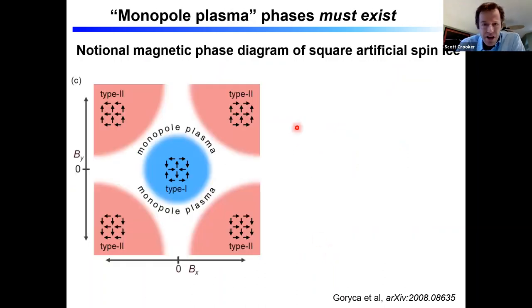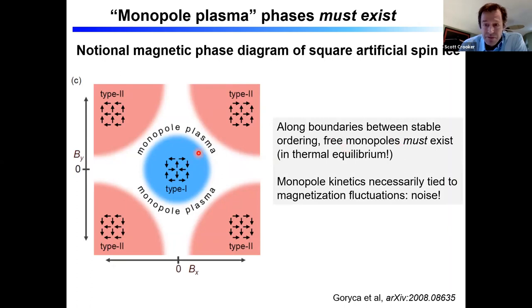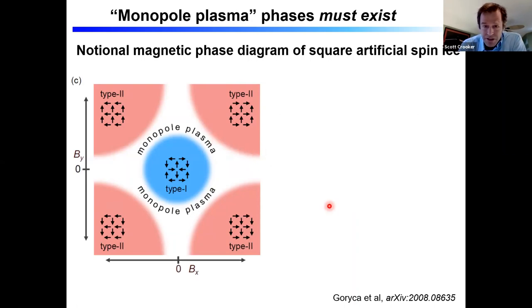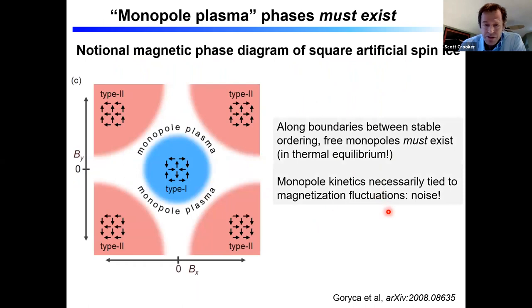So what we were interested in is just the realization that monopole phases must exist, even in square spin ice. So if we think about just a notional magnetic phase diagram of square lattice. So this is meant to be magnetic field along the y-axis, this is magnetic field along x. This is zero magnetic field right here. It's stable type one order, as we discussed. As we also discussed, we have here at large fields, we have stable type two order, but at the boundaries, freely moving monopole excitations must exist, even in thermal equilibrium. And because monopole kinetics are necessarily tied to fluctuations, we should be able to measure that with a noise spectroscopy.